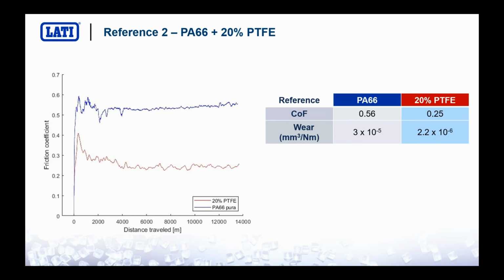As you can see on the right table, but also on the curve, the friction coefficient is more or less half of the polyamide 66, and also the wear resistance, the wear factor, is one order of magnitude lower than the polyamide 66. So we had a dramatic improvement of both wear and friction. Let's start to see what we tested.